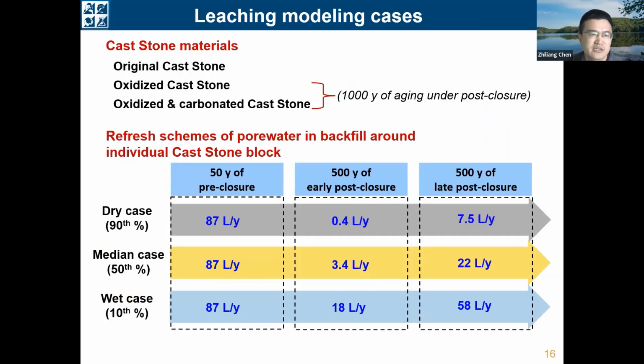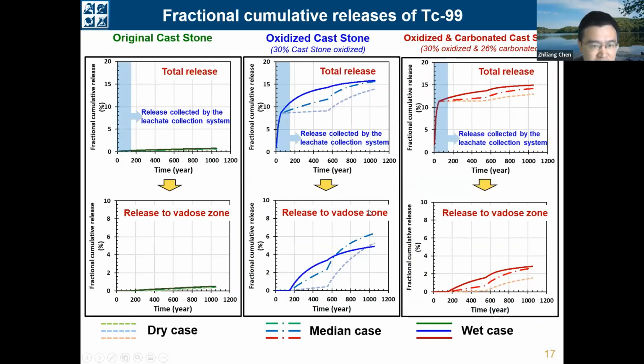And for the leaching modeling cases, we use different Cast Stone materials and different refresh schemes of the pore water in backfill to conduct sensitivity tests. So specifically, we have 3 different Cast Stone materials, including the original Cast Stone, the oxidized Cast Stone, and also the oxidized and carbonated Cast Stone. And each Cast Stone material is in different water saturation conditions, including the dry case, medium case, and the wet case. And here we have the modeling results regarding the fractional cumulative release of the technetium.